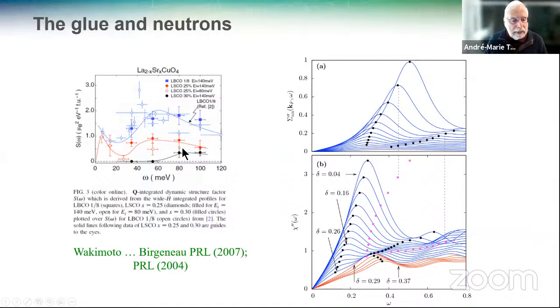And if you look again at neutron scattering, and you look now at this peak, this is in the superconducting state. And if you go to the normal state, that moves this way. And if we look at this high energy peak, when we go to the normal state in red here, that's also what happens. So this shows that the glue is this kind of a thing, right?